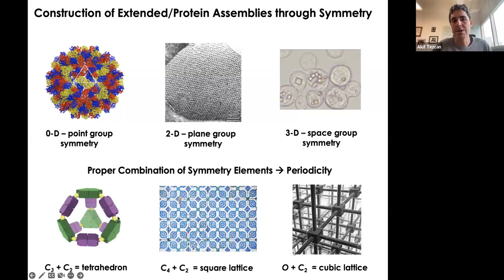And the key to making such architectures is to combine different symmetry elements to get periodicity over certain dimensions. So for example, to get a tetrahedral architecture that is a point group symmetry, you can combine C3 symmetry with C2 symmetry in a certain angular relationship, 54.7 in this regard. You can take a C4 symmetric assembly and combine it with C2 symmetry to get a planar assembly, or you can have an octahedrally symmetric building block and combine it with C2 symmetric connections to get a 3-dimensional lattice, a cubic lattice. So what we wanted to do is use these types of strategies to make these types of architectures.